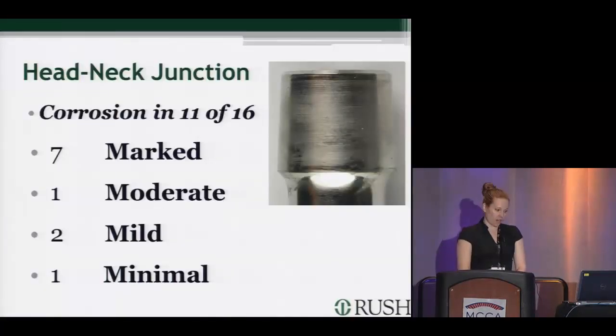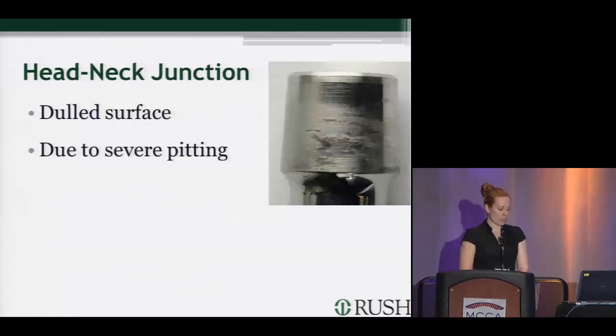Turning to the head-neck junction, corrosion was observed in 11 of the 16 cases. In 7 of these cases, the corrosion was graded as marked. In 1 of the cases, moderate corrosion was observed. 2 of the devices demonstrated mild corrosion, and 1 case demonstrated minimal corrosion.